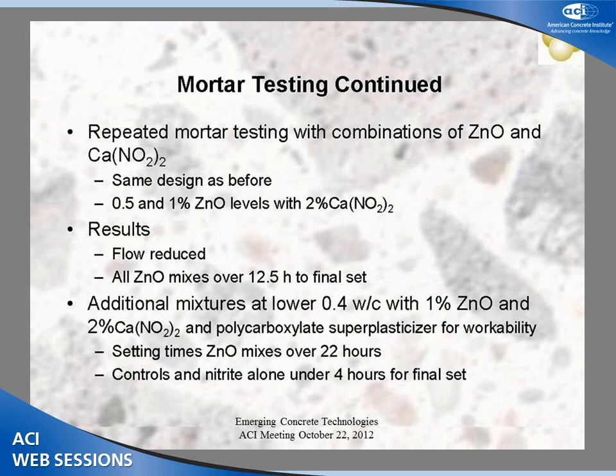So some repeated mortar testing was conducted with combinations of zinc oxide and calcium nitrite, basically the same design as I talked about in the previous slide. This time we looked at 0.5% and 1% zinc oxide with 2% calcium nitrite addition. Some of the results that we saw were that the flow was reduced, and that all the mixtures that had zinc oxide had time to final set of over 12.5 hours. So again, we saw a very notable amount of retarding imparted by the zinc oxide.